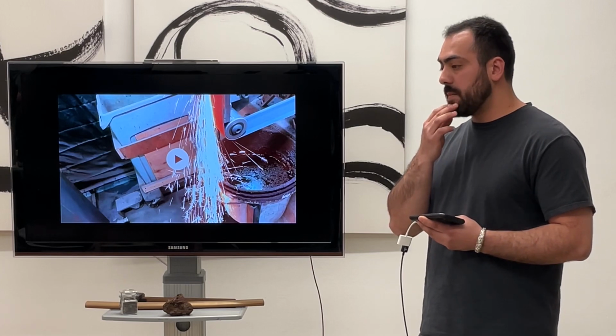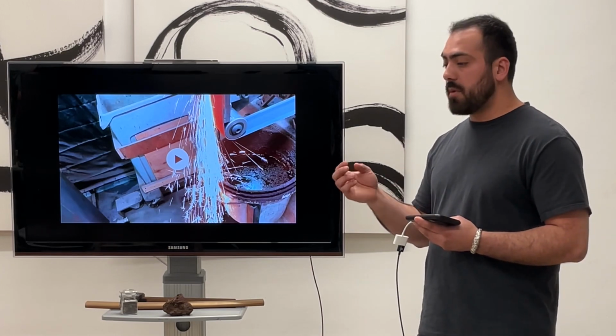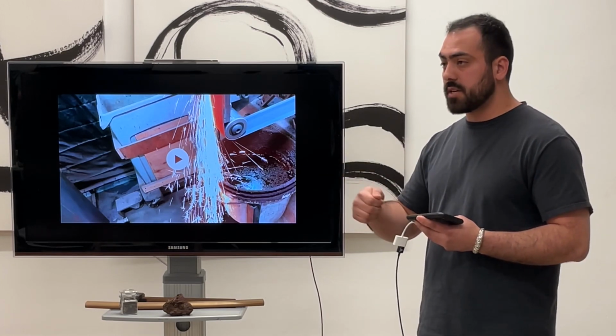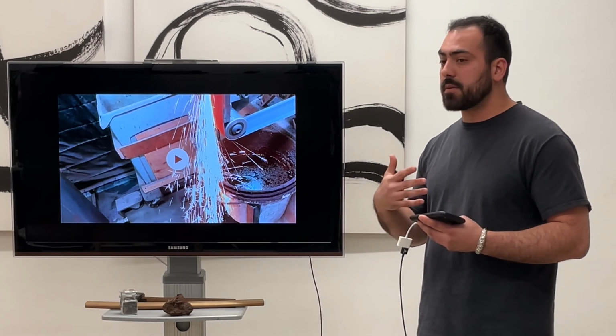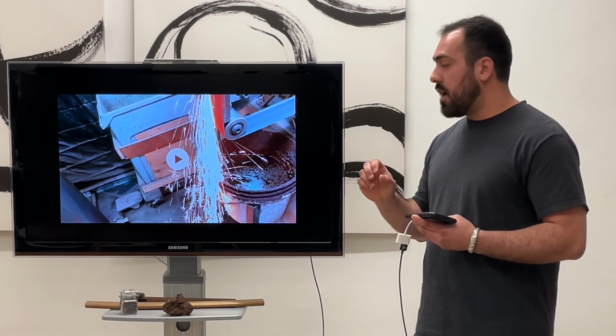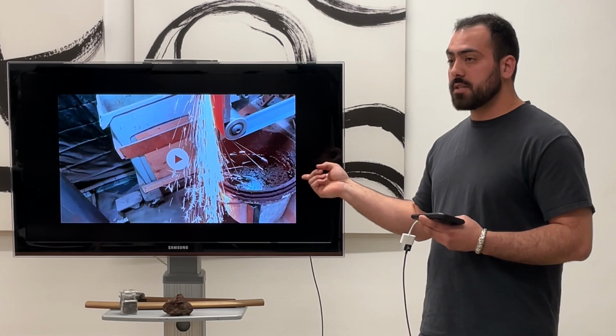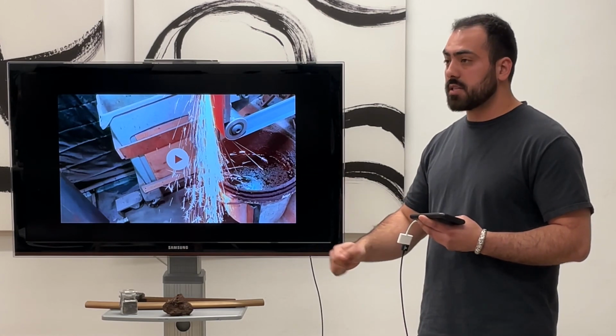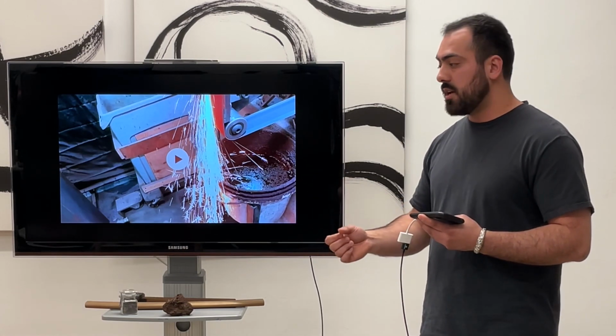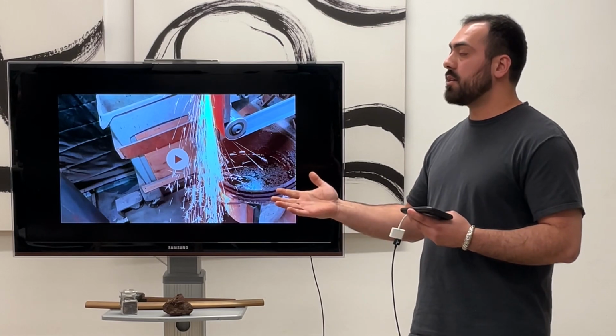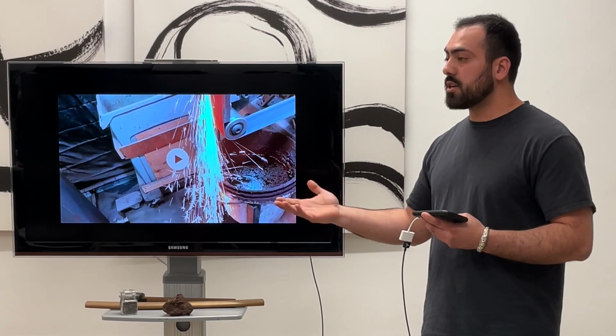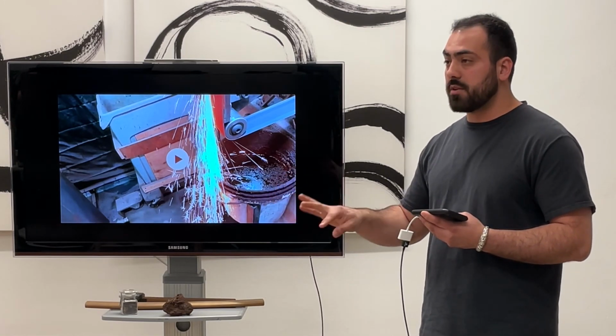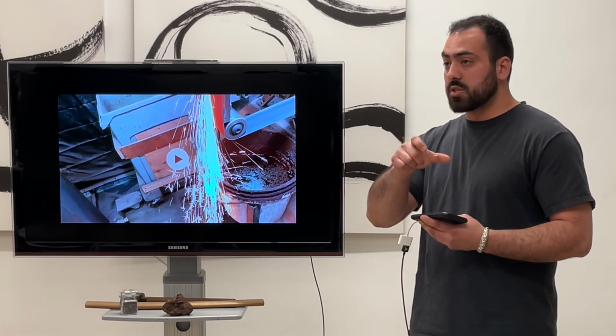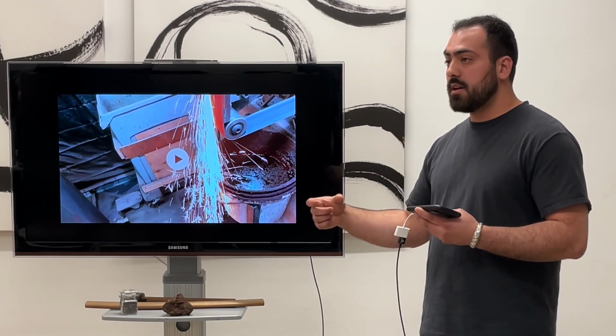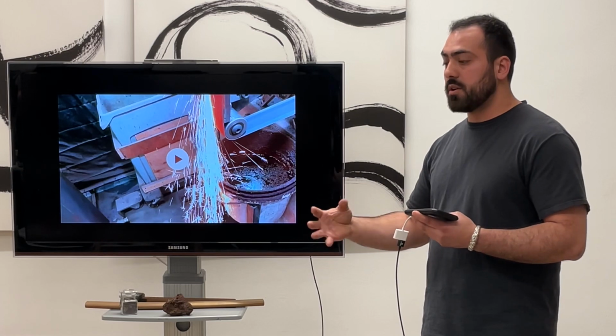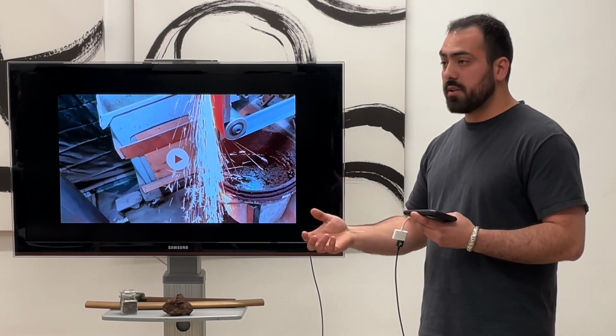The ha, in terms of Rockwell, I have chisels for testing Rockwell on my production stuff, like my regular work. Out of the water, it's over 64 Rockwell, which is, for instance, a good kitchen knife will be between 59 and 61 generally. So it comes out screaming hard, and I have to temper it back by heating it up to a lower temperature in order to make the steel less brittle.